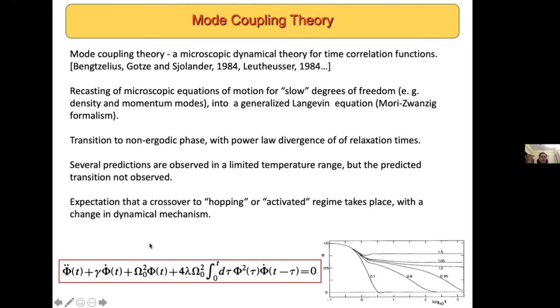I've written down the schematic mode coupling theory equation of Leutheusser just for reference. The basic thing to notice is that this is an integro-differential equation, and the integral involving the memory function has the correlation function themselves and the time derivative. And what goes into defining the memory kernel, I didn't put this down here, is information about the structure of the liquid. And so with structural input, you have a theory that predicts a transition to a structurally arrested state.